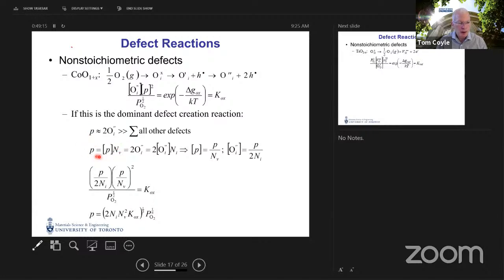Manipulating the definitions of these expressions, we can derive relationships between the hole concentration and the oxygen interstitial mole fraction, so that we can substitute for, in this case, the interstitial concentration in terms of the hole concentration. And so now we have within our mass action or equilibrium constant expression only holes, which is what in this case we're looking for.